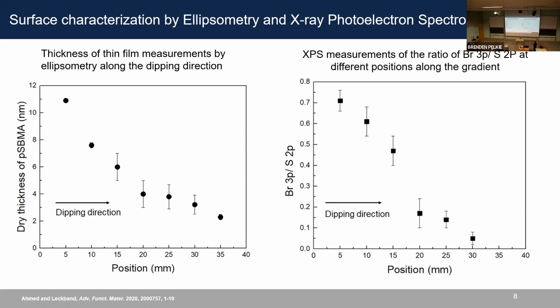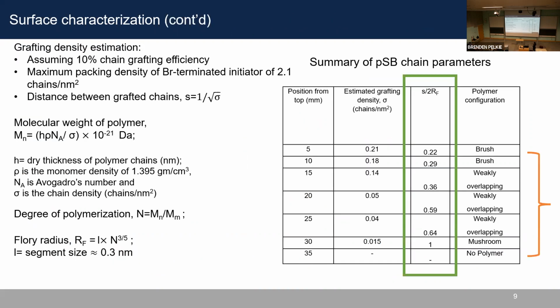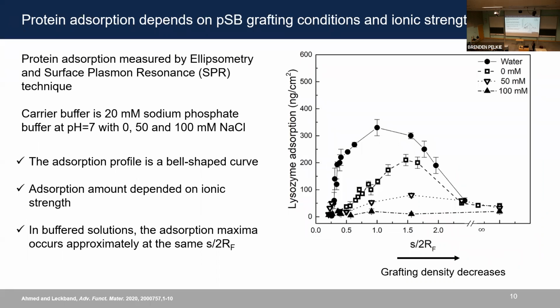And we also used X-ray photoelectron spectroscopy to measure the chemical composition of the thin film. And from the bromine to sulfur ratio, we estimated the distances between the grafted chains, which is the inverse square root of the grafting density. And from the thin film dry thickness, we can estimate the molecular weight to determine finally the S/2RF ratio. And there's lots of things going on, but the idea is to graft different polymer configurations on the same substrate. And it ranged from brush to weakly overlapping to mushroom-like chain. And then we monitored protein adsorption.